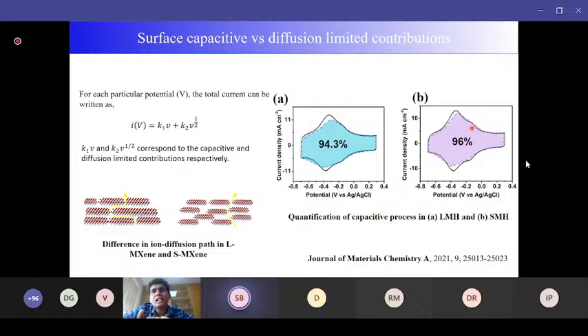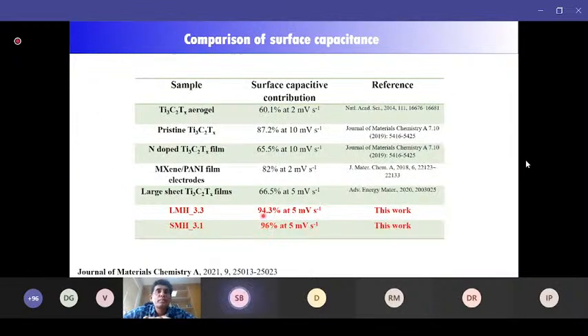Now we have found that this shaded region shows that 96% is capacitive limited, this surface limited. That means most of the surfaces are getting accessed within this freestanding hydrogel structure, either in the smaller seed size or the bigger seed size. This indicates that the hydrogel structure has a very good porosity, and the continuous porosity leads to accessibility of the ions to the individual seeds, and this leads to the good capacitance also. And this is some comparison chart with some previous literatures.